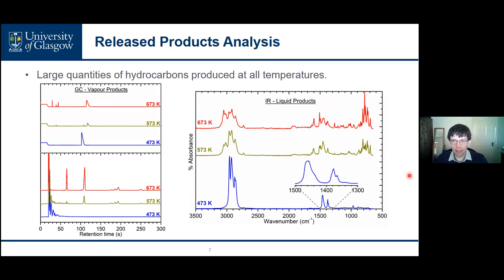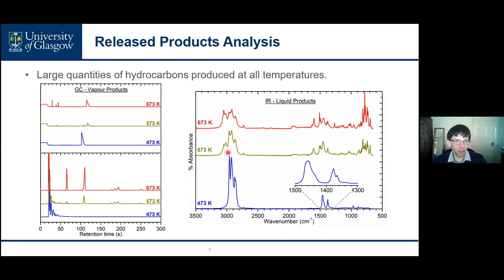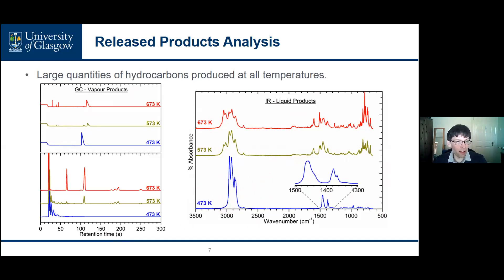In the case of the reaction at 473 Kelvin, the released products are almost exclusively saturated alkanes with no significant levels of aromatic production, as is visible in the infrared spectrum, and the GC column is flat, together with quite a large proportion of unreacted propene due to the ongoing deactivation.